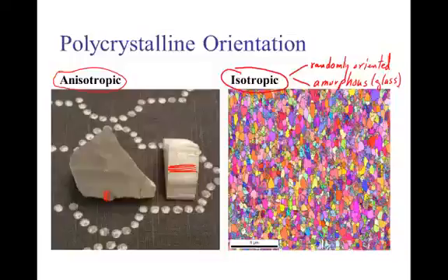And so we're bringing back this nice microstructure of zirconia that we have on the right side. And I want to point out that the crystals in the micrograph don't have different colors just to distinguish them from each other. They have different colors because they're color coded according to which side of the crystal is pointed at the camera in the microscope. And so by the variety of colors, you can see that they have all different orientations at random through the structure. So that's the most common case for most materials, to have a random microstructure.